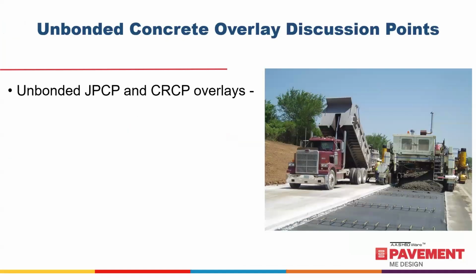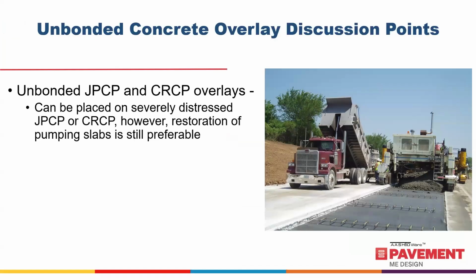Okay, so let's talk a little bit about these overlays. For these, you can place them on severely distressed jointed plain or continuously reinforced concrete pavement. I'd say the caveat to that is if you have a serious pumping problem, that may be really testing the limits of the concrete overlays. And I still think it's prudent to either undercut, replace them, or underseal. Maybe sometimes even have to jack the slabs a little bit to restore the original profile before placing the overlay.